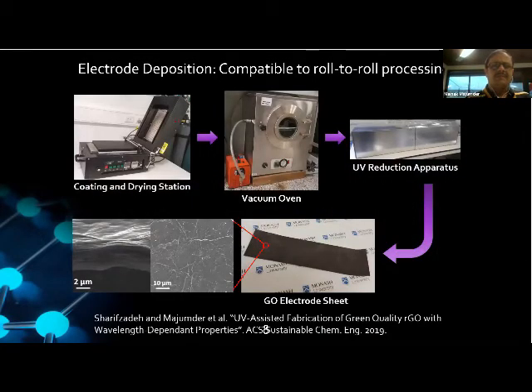The process of making the electrodes is quite simple. It is compatible with roll processing. We coat, we vacuum dry, and this UV reduction is an important aspect of our intellectual property we have developed. I will talk about it on the next slide. And then essentially you have made this electrode, and you're limited only by the size of your bulb or UV lamp, so you can make electrodes as large as possible.